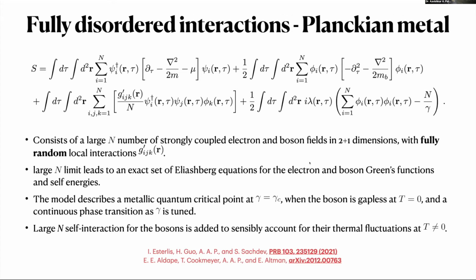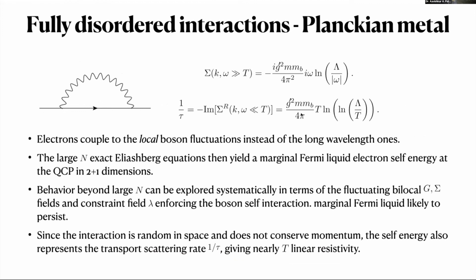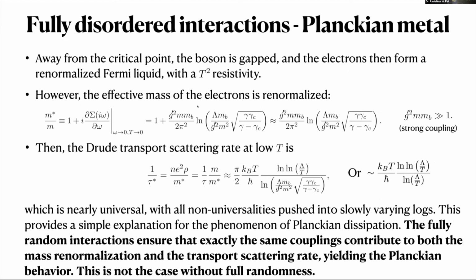finite temperatures. You can tune it to a critical point, and what one gets within the large N framework is a scattering rate that's T log T, and that also represents a transport scattering rate, giving nearly T-linear resistivity with a log correction. But the nice thing here is you had only one interaction coupling that's fully random, which was G prime. So when you look at the renormalization of the effective mass, that is the single particle self-energy, it doesn't have to do with transport. It's only G prime that contributes. There's no additional interaction contributing to it. So you have the same interaction contributing both to transport and to mass renormalization.